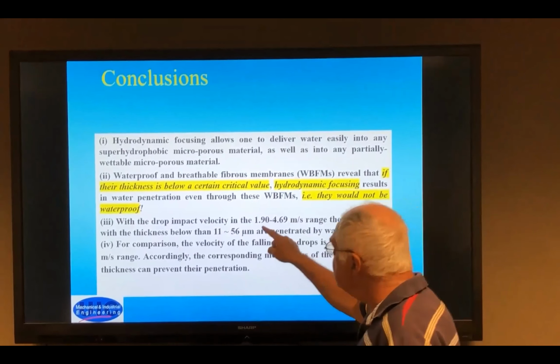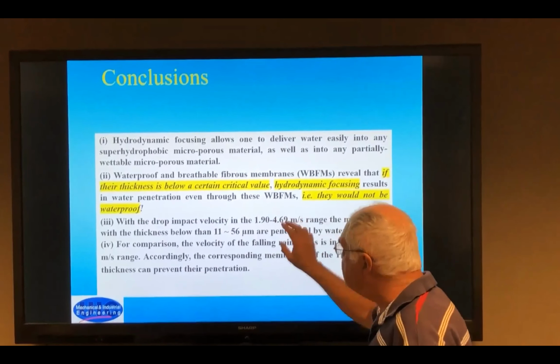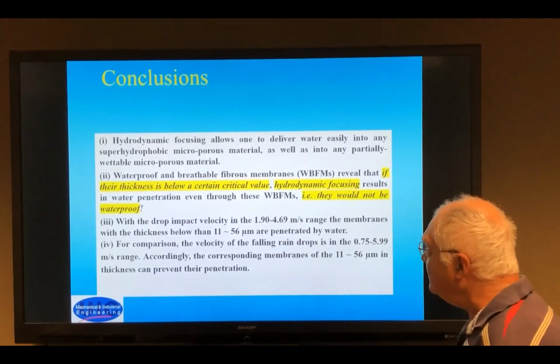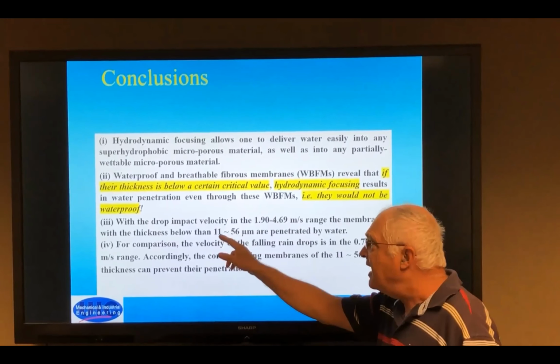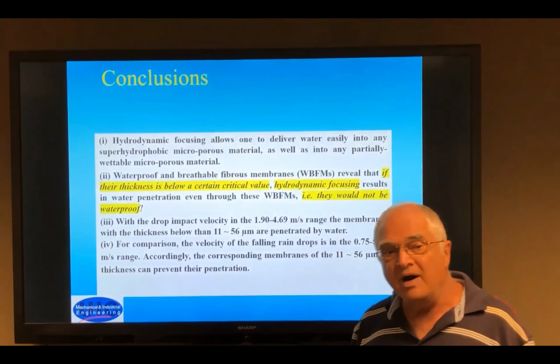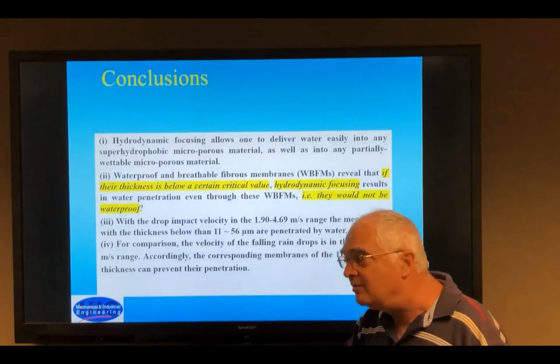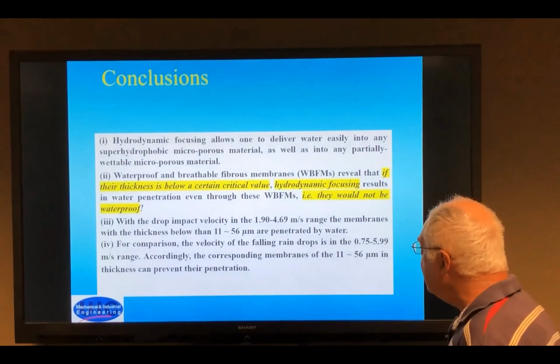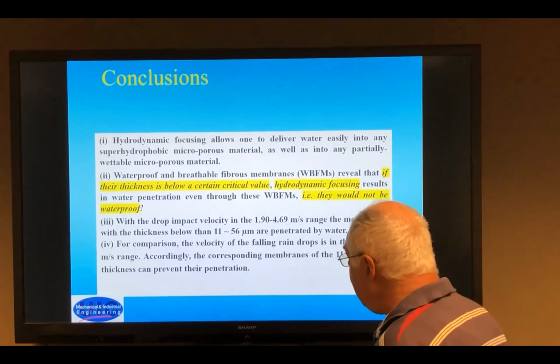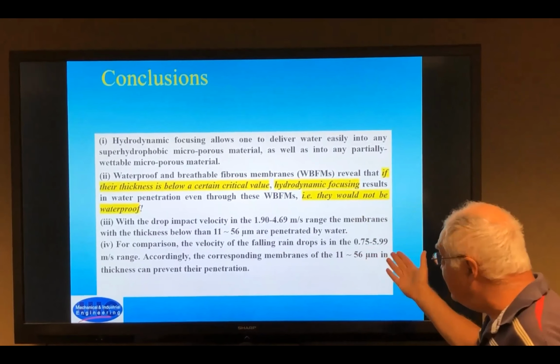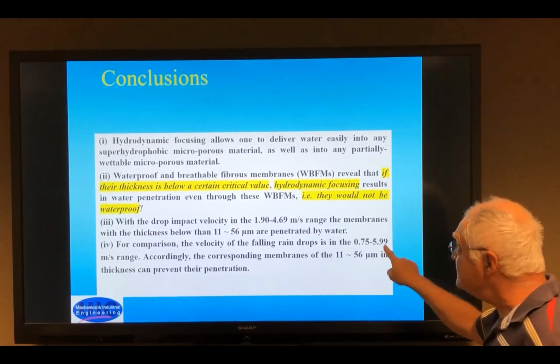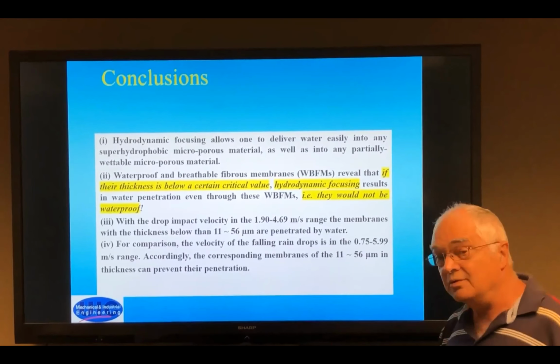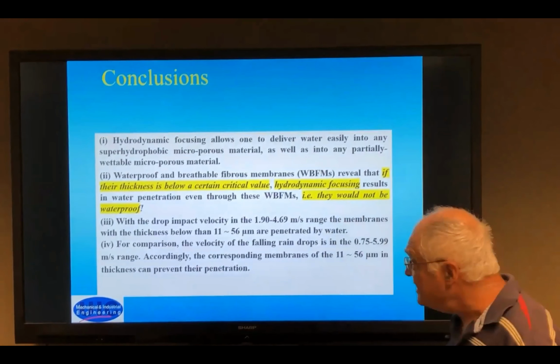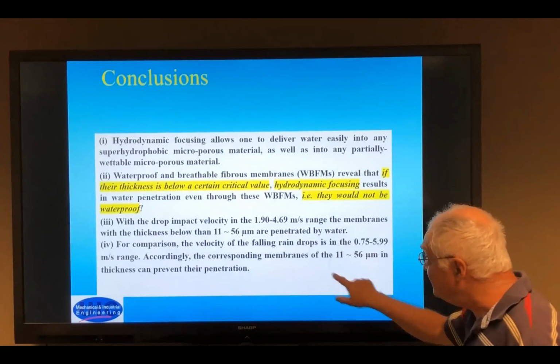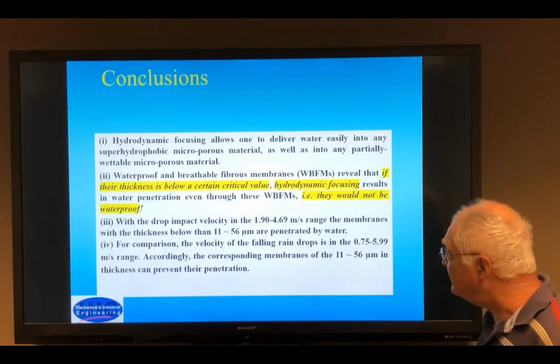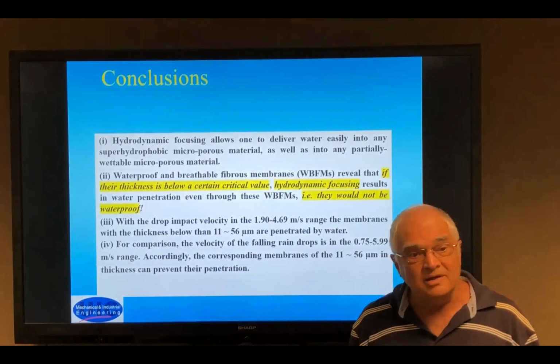Now we show that essentially in the range up to 5 meters per second, what will guarantee waterproofness would be membranes in the range of from 11 to 56 micrometer, not less than that. Less than that, water droplets will go through the membrane. For comparison, I'm telling you that water drops can go up to 6 meters per second. Therefore, to be sure that you have protection from water droplets during rain, for example, you have to have at least a thickness of 11 to 56 micrometer, not less than that.